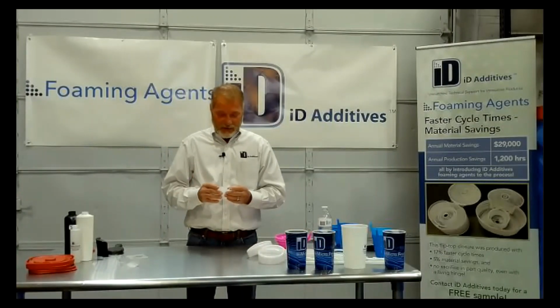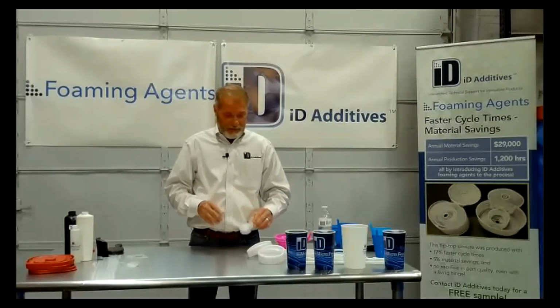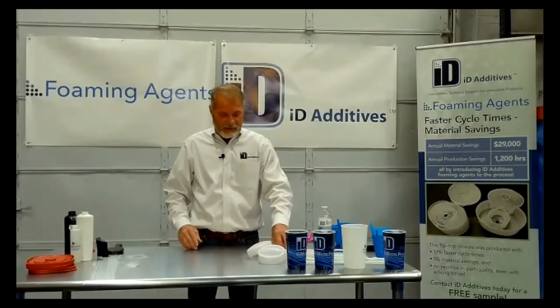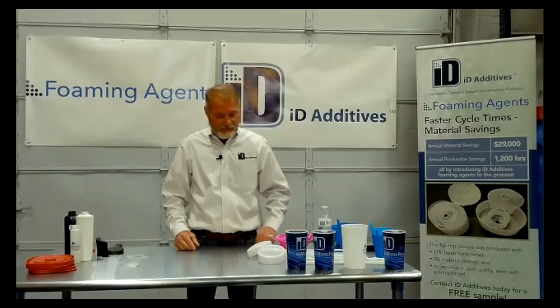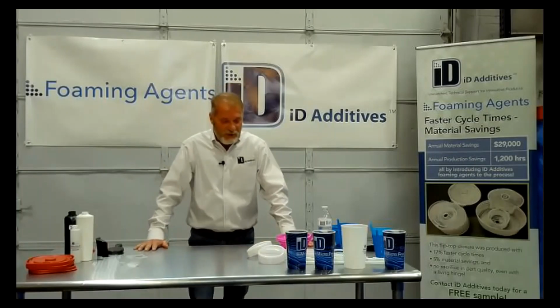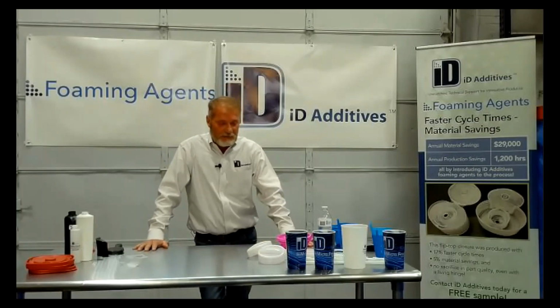But these caps, we dropped the energy to 10% on the caps, and then we did like a door hinge thing, and it was around 18% energy reduction. So whenever you're dropping barrel temperatures, you're saving energy, bottom line.